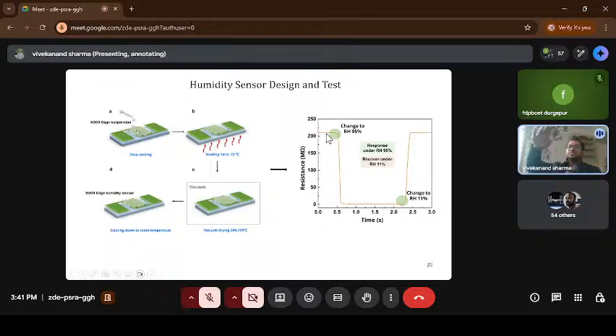In this graph, you can see this cage has shown very high resistance, like very low conductivity. In absence of any water molecule, like when there was no hydrogen bonding, this cage material behaves like an insulator. But when we change the surrounding medium and add a lot of water vapor in the system, so the relative humidity goes up to 95%, we have found a very sharp decrease in the resistance. It means that the overall sensor becomes very, very conductive. Here we have plotted this resistance versus time graph.